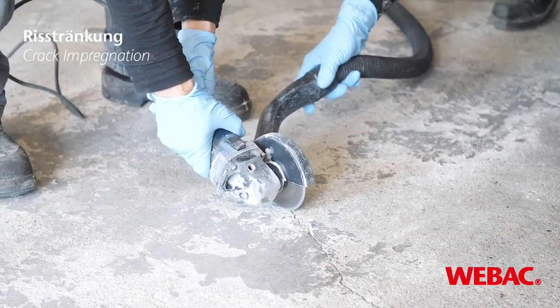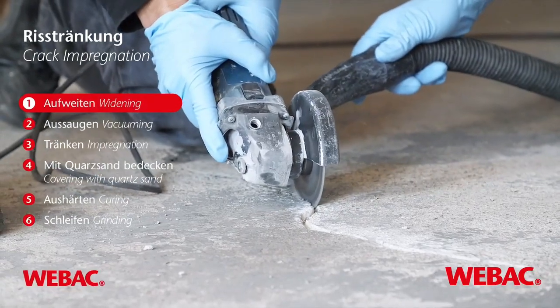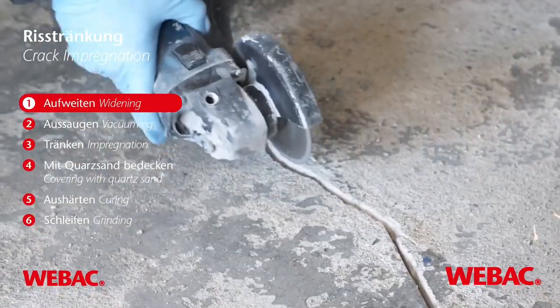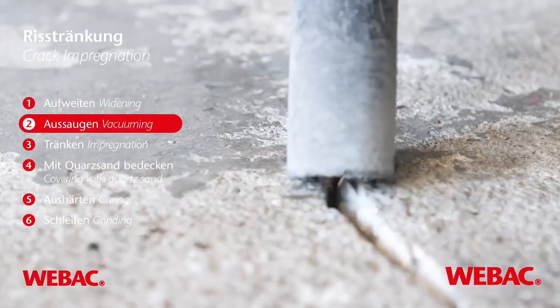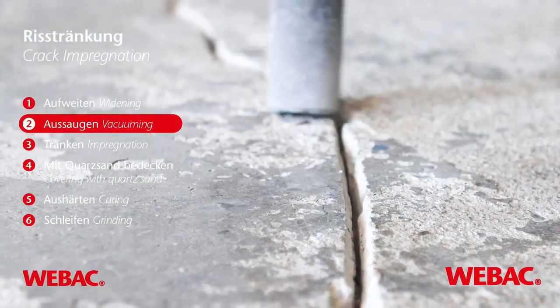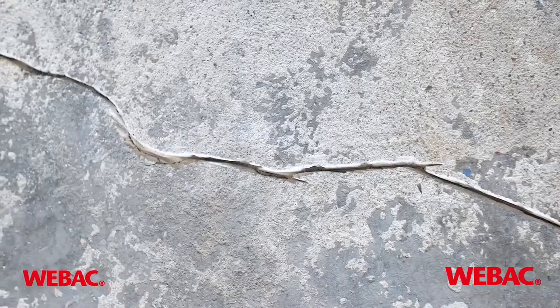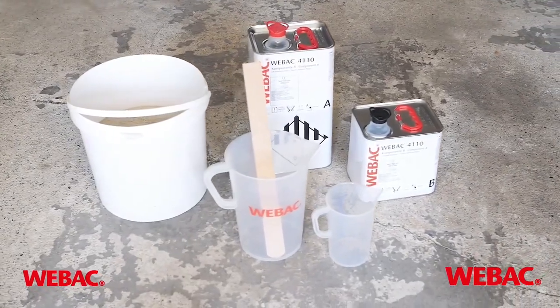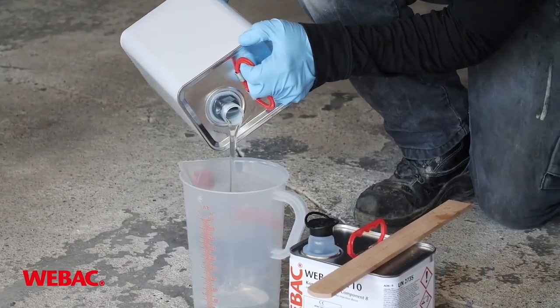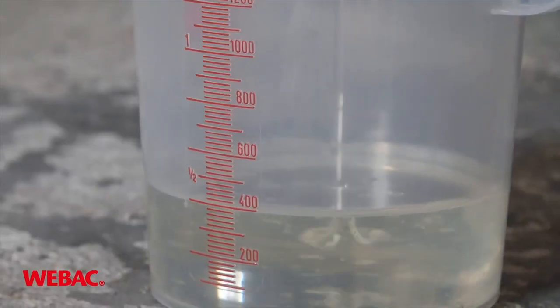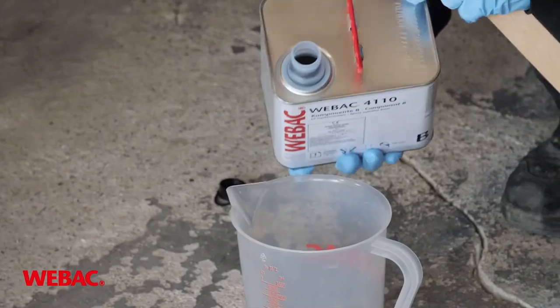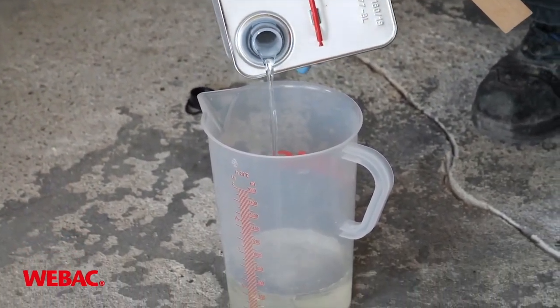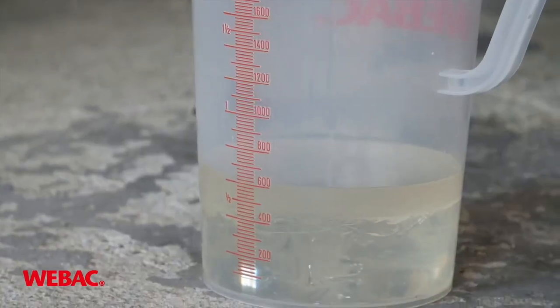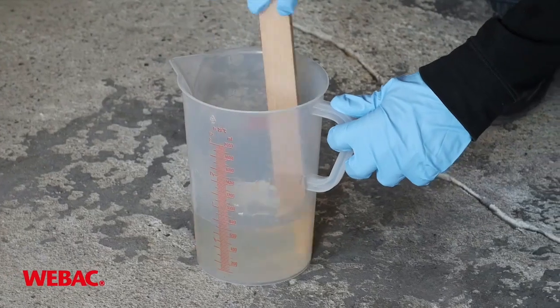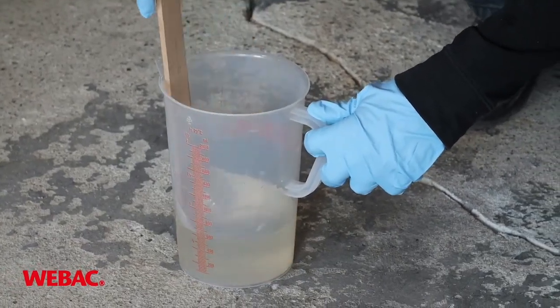As you can see, first of all you have to make sure that the crack is wide enough. So you use a grinder to widen the crack, and afterwards you suck the drill dust out of the crack so that the injection resin is able to penetrate it. Now we are going to show you the mixing. Most of our products are two-component based, so you have to mix both components prior to application. The mixing ratio can differ, so you need to make sure that you mix the product in the right ratio.